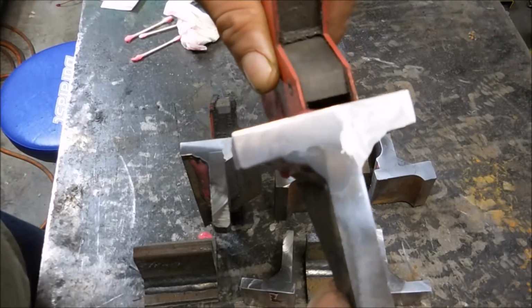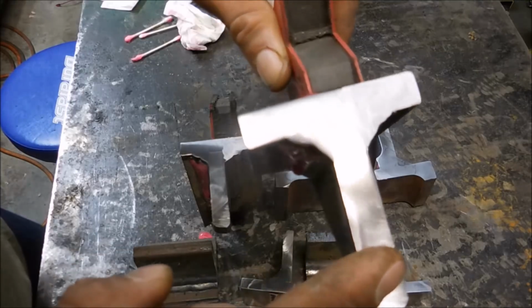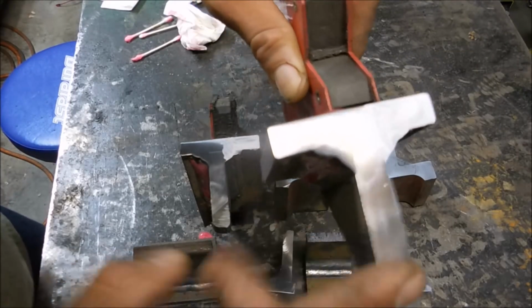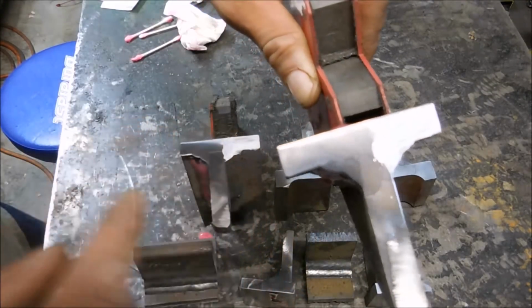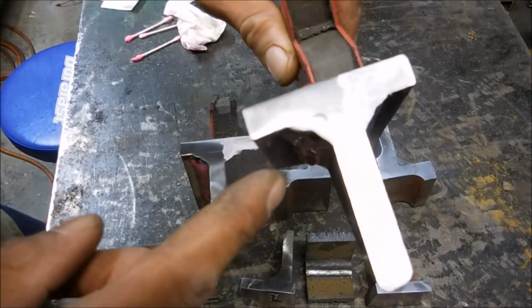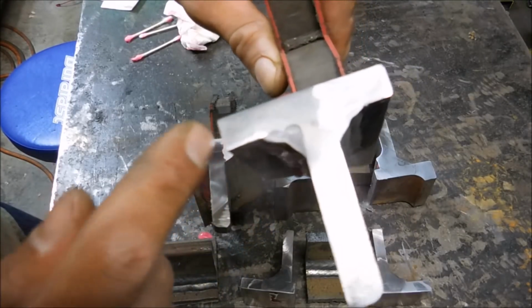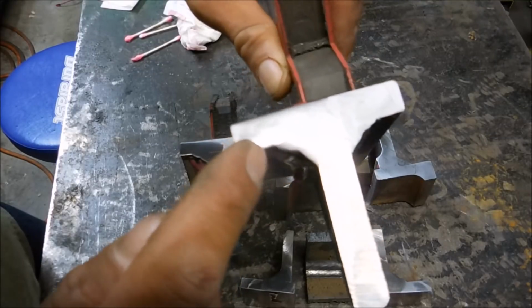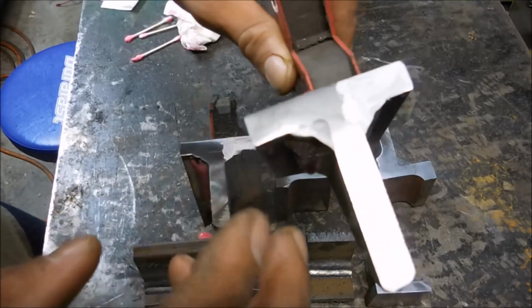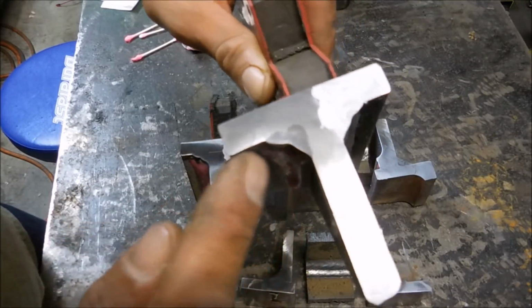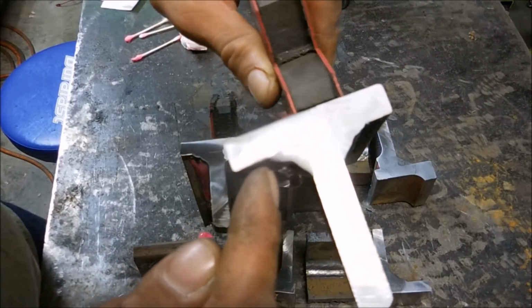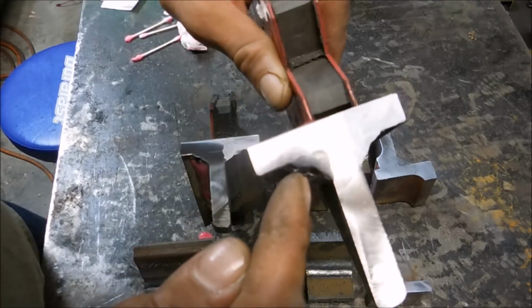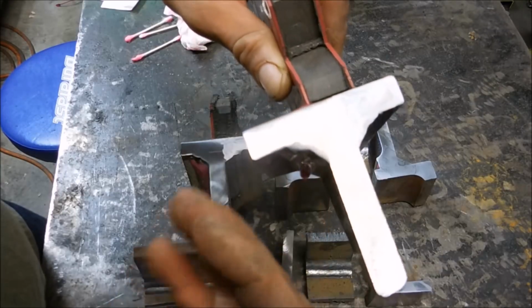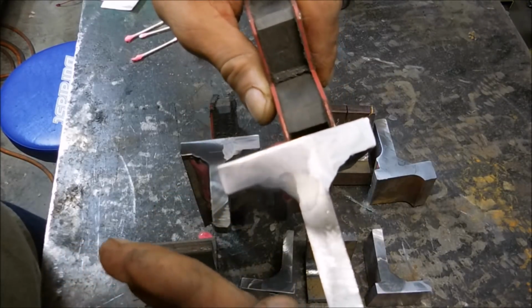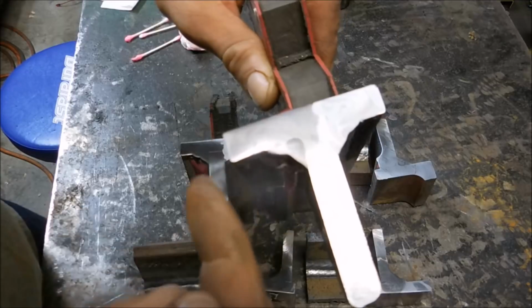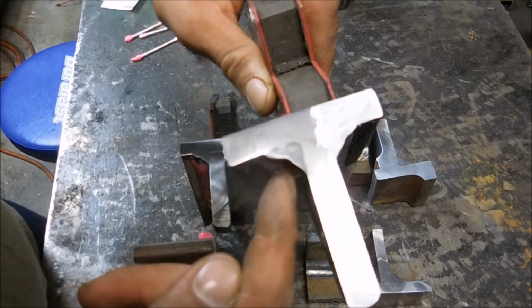Okay, so what we're looking at here is the coupon that I welded 3 passes back to back without chipping the slag. I don't see any slag inclusions in there. There's pretty good penetration. However, I think I would have turned up the settings a little bit more. And what I can see is the weld nugget for the second and the third pass on the cap pass, right? They're not stacked properly, right? There's actually a little valley that runs down there.